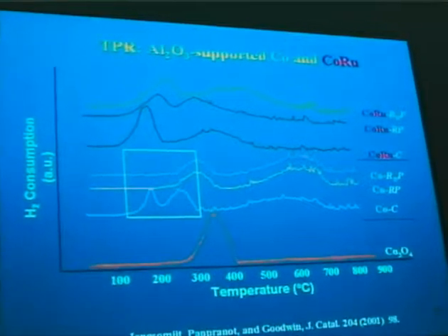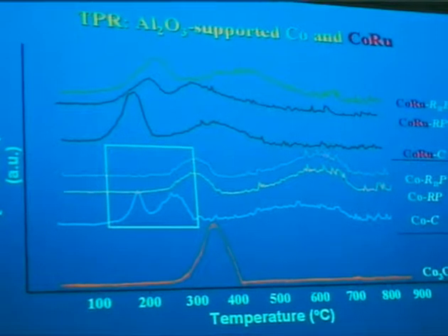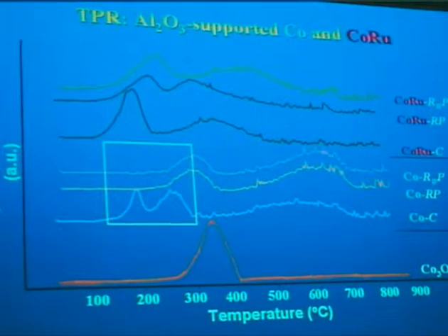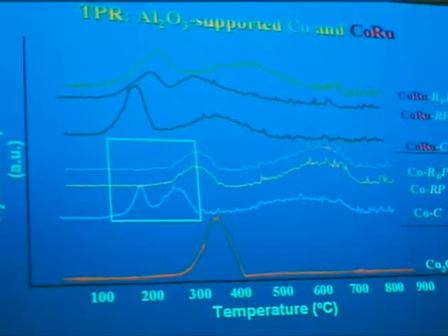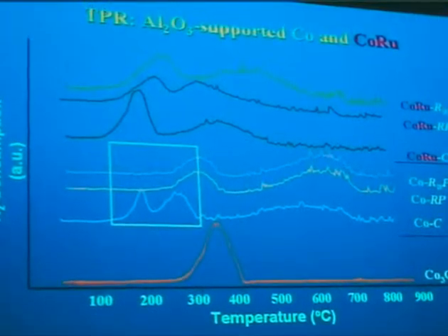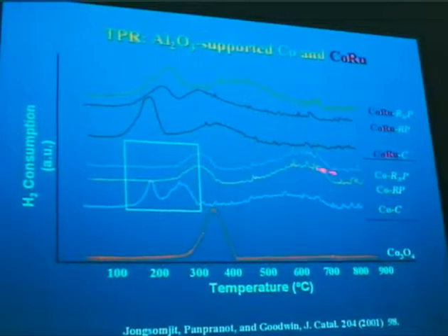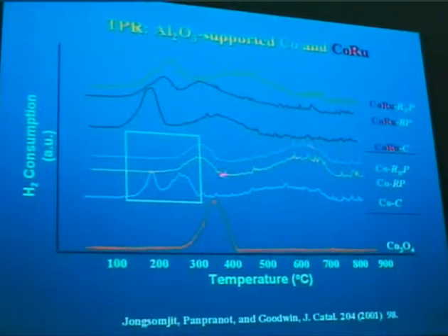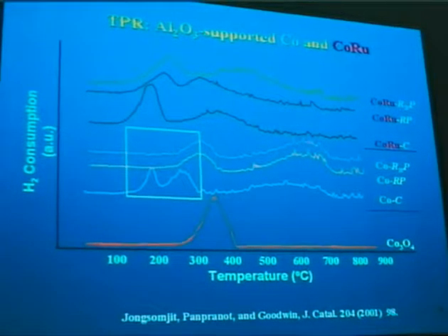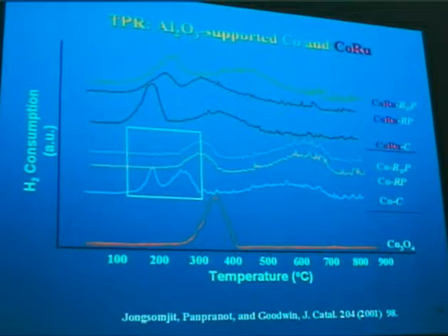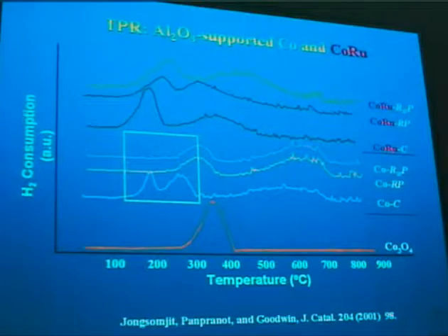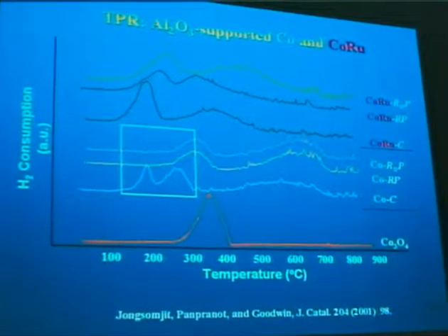But once this catalyst goes through reduction, it becomes harder to reduce, and you can see a drift upward in temperature of the reduction peaks. On the other hand, when you add, and by the way, this is more typical of the catalyst that you're using, because you don't do reduction in a TPR mode with 20 milligrams of catalyst or whatever. That's not a normal reduction for a commercial catalyst.